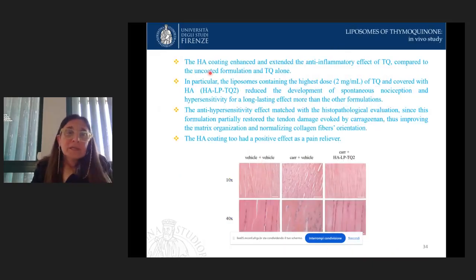The results show that the presence of the hyaluronic acid coating enhanced the anti-inflammatory effect of thymokinone with respect to thymokinone alone. Also in this case, the formulations ameliorate the bioefficacy of the molecules. The liposome containing high doses of thymokinone, in particular 2 mg per milliliter, and covered with hyaluronic acid results the best formulation. The anti-inflammatory effect is due to the presence of thymokinone, but also to the presence of hyaluronic acid around the liposome. The hyaluronic acid restores the tendon damage and improves the matrix organization, the tissue organization. This is also evidenced by histological study.